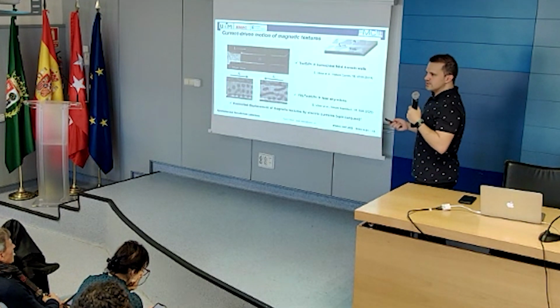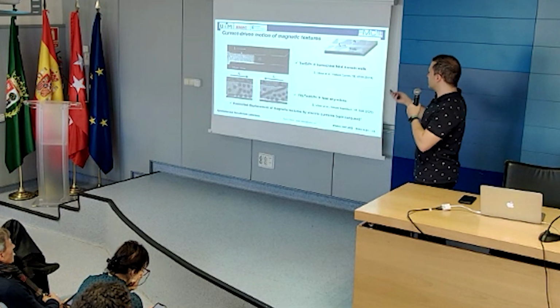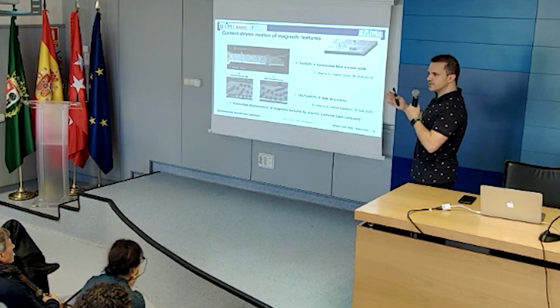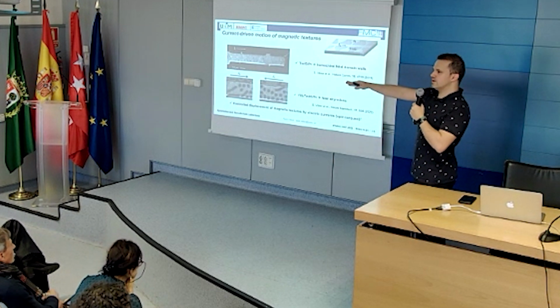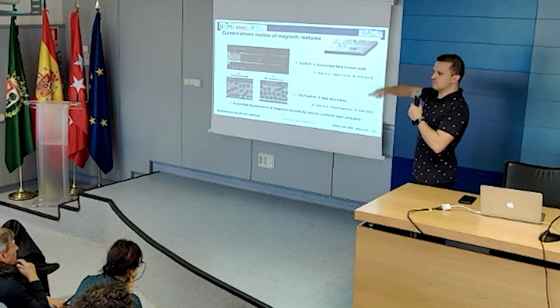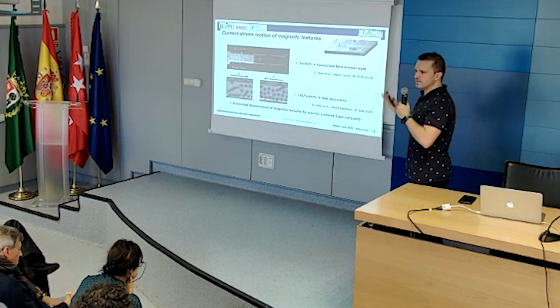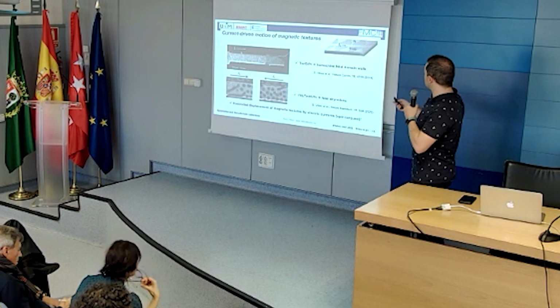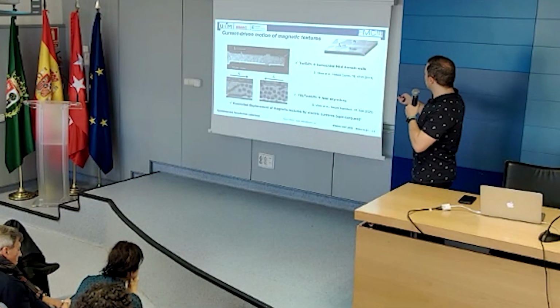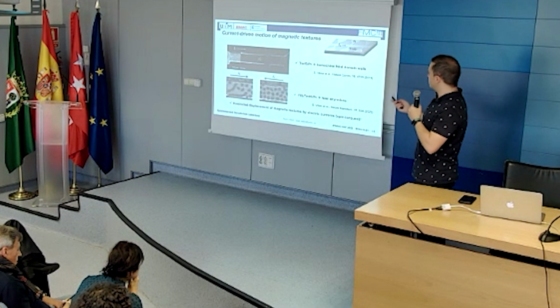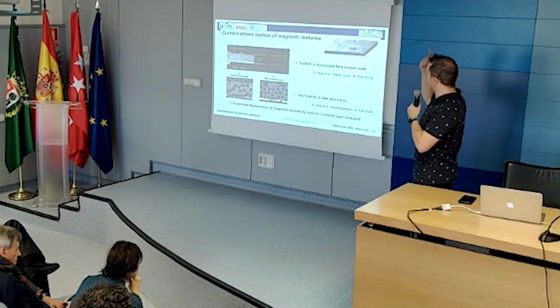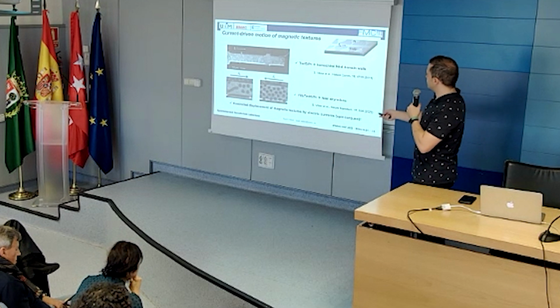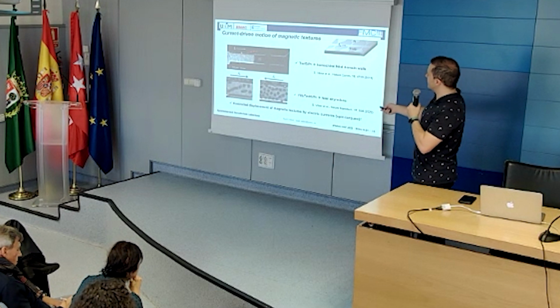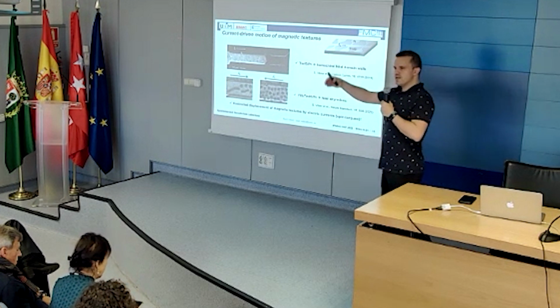Now what science can we do with this? We have this material with perpendicular magnetic anisotropy. We run some current through a platinum layer that is on top or on the bottom, whatever stack we are doing, it doesn't matter. This is how, for instance, this device looks. We have two ferrimagnets, that's the magnetic system of choice. We have out-of-plane magnetization for this one, and we run current through the platinum stripe. That's part of this device. So we run current, and then we can deterministically, so controllably, displace this domain wall.